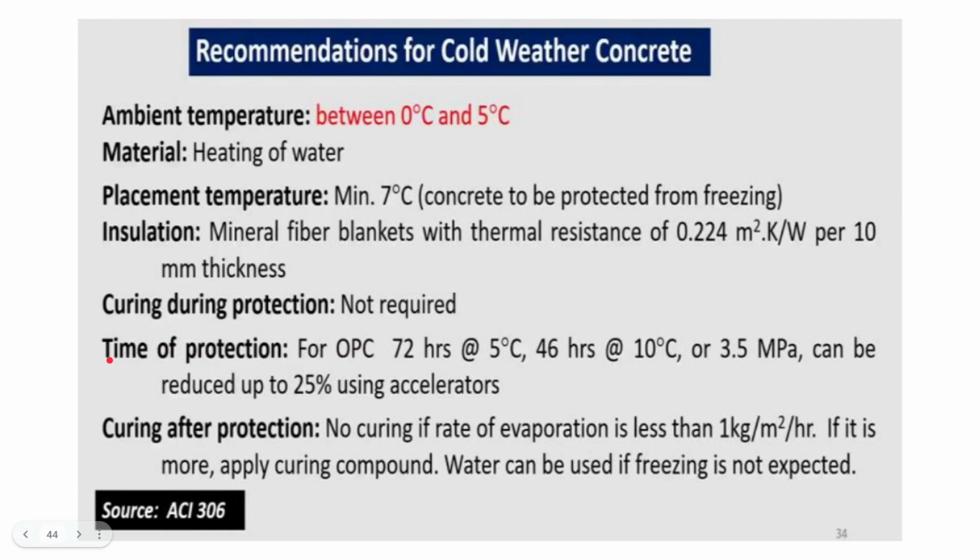Sorry, and the time of protection for OPC will be 72 hours at 5 degrees centigrade, 46 hours at 10 degrees centigrade, or 3.5 megapascal, and it can be reduced up to 25% using accelerator. So these are the times of protection. If it is 5 degrees, it has to be 72 hours.